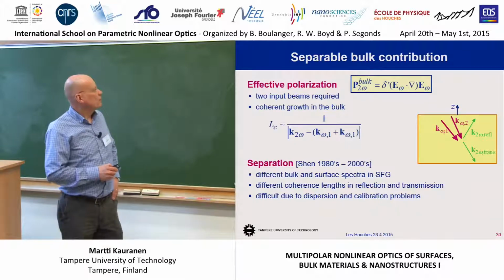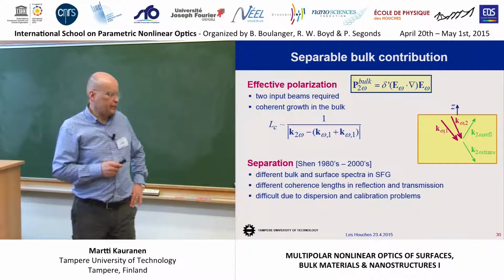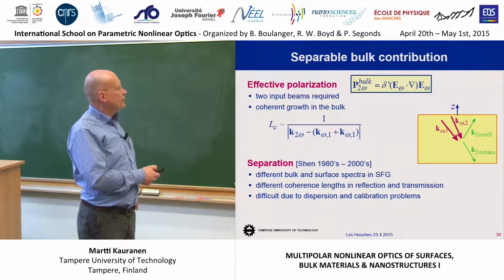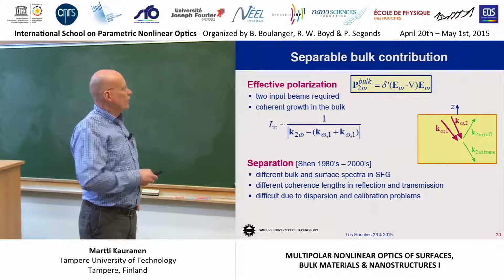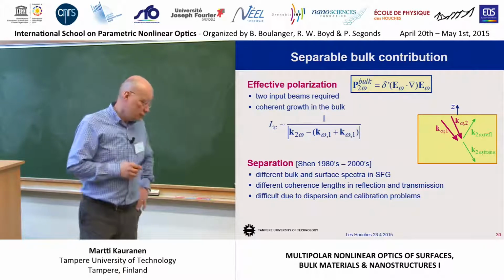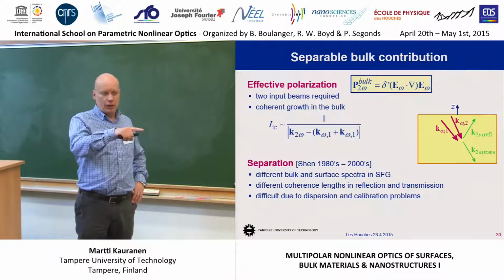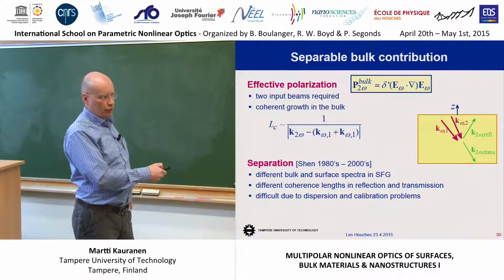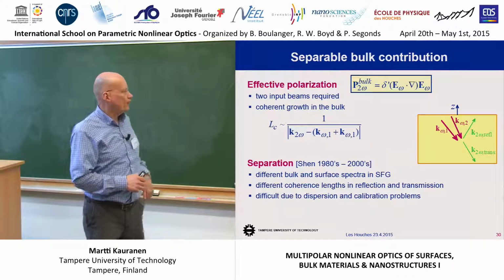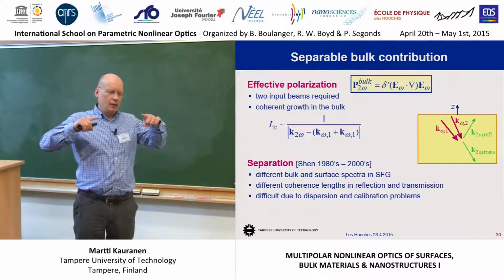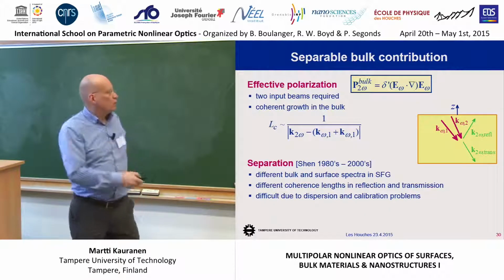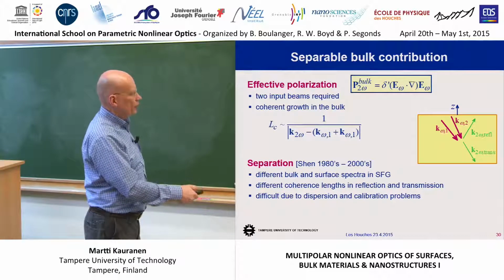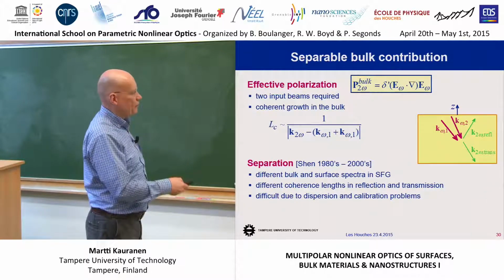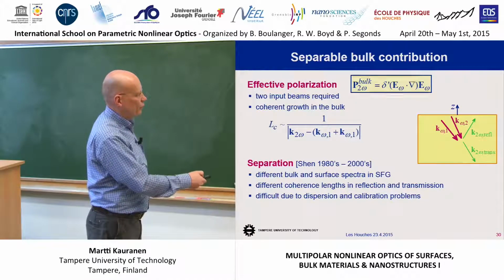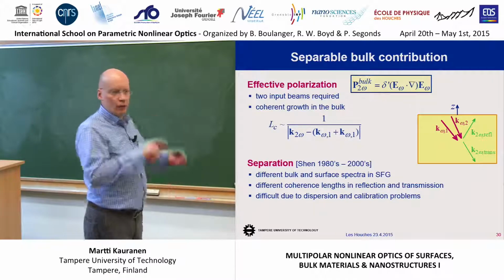And let's first try to think of experiments that could somehow access this delta prime bulk parameter. It turns out that if you do second harmonic generation with a single beam like usual, you don't couple to this term at all. So what you have to do is bring in two fundamental beams that intersect in the medium, like here, and then you have to measure the joint signal, either in transmission or reflection, that depends on both of these two beams. Of course, each beam separately creates a signal, like in this direction or in this direction, but we go somewhere in between and look at the joint signal, okay?